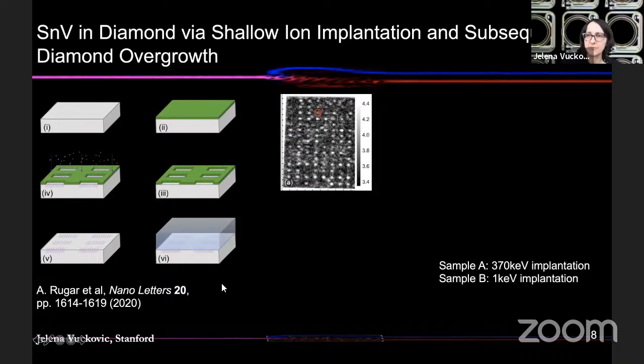The second advantage is that for 1 kiloelectron volt acceleration, you can use very simple masks consisting of resist. This is just a very simple ZEP mask or other resist that you use for your e-beam lithography. That mask can resist 1 kiloelectron volt ions, meaning that you would only perform implantation at the desired positions. That's not something that you can use for very high acceleration energies, because this mask would simply not prohibit highly accelerated ions from entering everywhere inside of diamond. So you will have them randomly positioned in the structures. And that has been a big issue in the previous experiments.